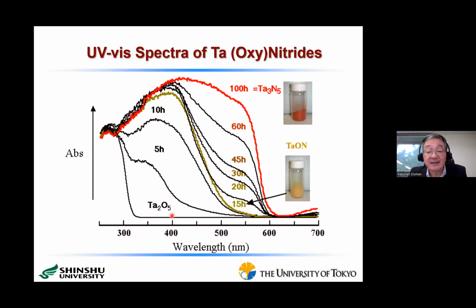Okay, this is the starting material, tantalum pentoxide, a white colored powder. Then after starting the nitridation, a new peak appears here. After about 15 hours, the absorption edge is located at about 500 nanometers. Then we obtain this kind of yellow colored powder. This is actually tantalum oxynitride. Then after that, a new band appears here. After 100 hours nitridation, the absorption edge shifted to about 600 nanometers. Then we get this kind of red colored powder. This is Ta3N5, which is confirmed by XRD pattern.